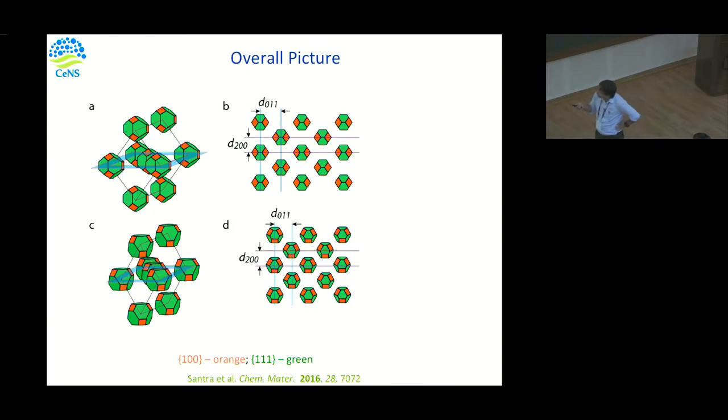And in this case, why does this particular phenomenon happen? Why do we observe this? So in this case, I only have the idea of, basically this molecule, oleic acid, it has a COO, a carboxylic acid group at the end, which binds to the lead of this lead sulfide quantum dot.